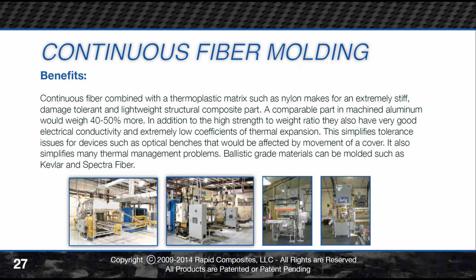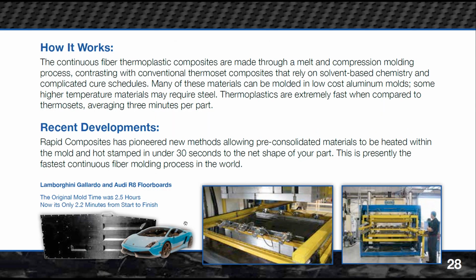To give you an idea, that process typically, even in some of the largest components that we make, can be in less than 5 minutes, pretty much categorically. And that's even when you're running polymers like PEEK, polyether ether ketone, that's very high temperature and requires about a 780-degree Fahrenheit melt point. So it's a very fast process. There are limitations, and one of them is that it typically wants to be a continuous thickness. We'll get into more detail on that in a bit.